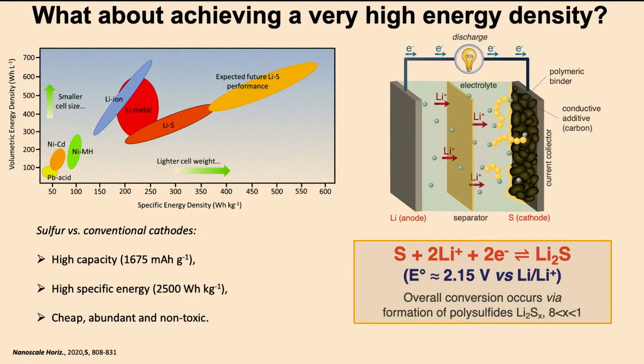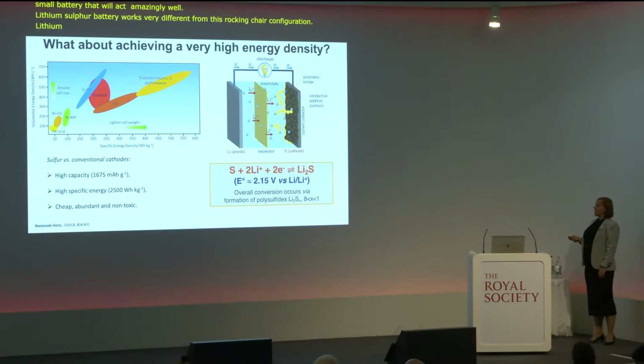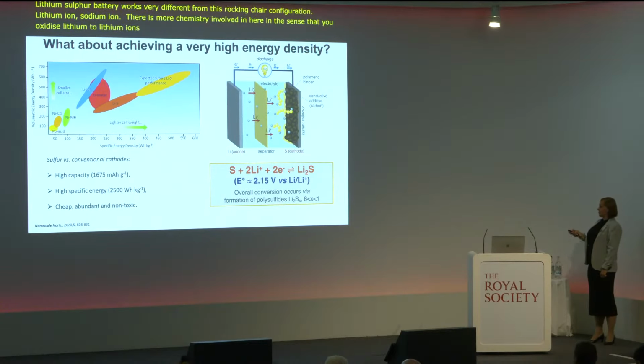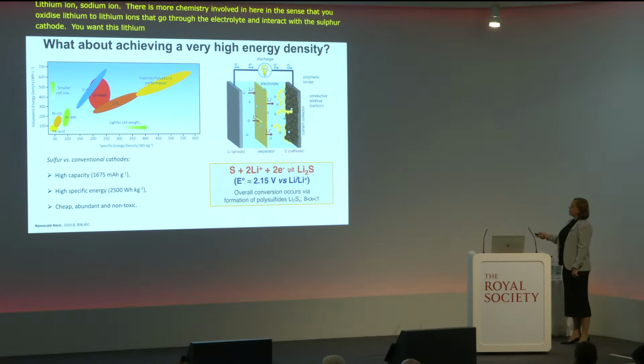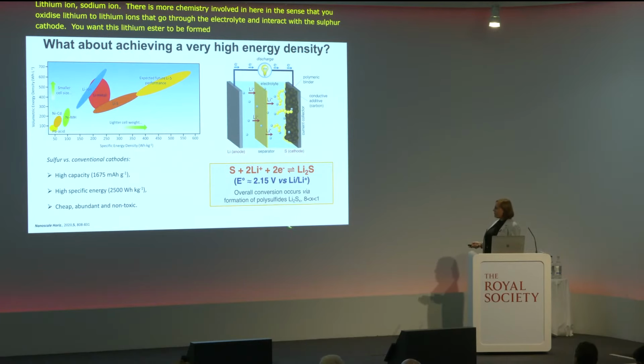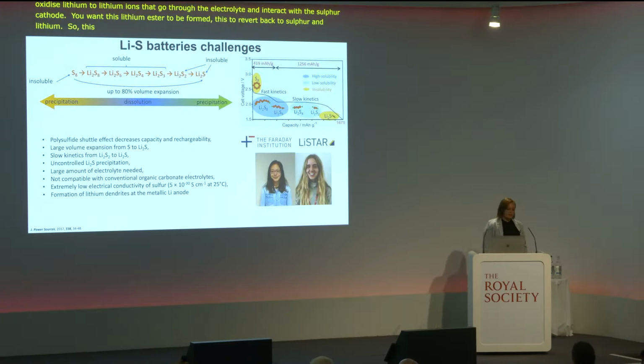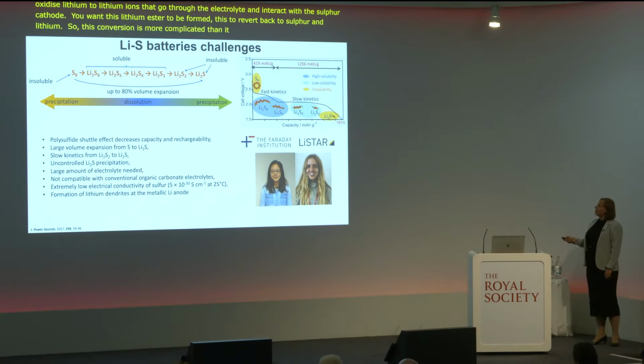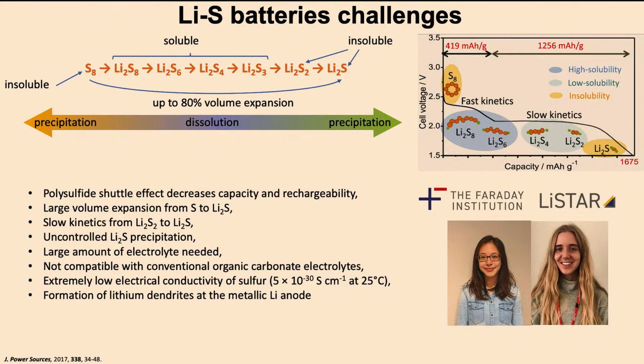Now, lithium-sulfur batteries work very differently from the rocking-chair configuration of lithium-ion and sodium-ion. There is more chemistry involved, in the sense that you oxidize lithium to lithium ions that go through the electrolyte and interact with the sulfur cathode, and what you want is Li2S to be formed. And then you want this to revert back to sulfur and lithium. This conversion is more complicated than it should be, so unfortunately you don't go directly to Li2S, but through a lot of polysulfide intermediates. Some of these polysulfides are soluble in your electrolyte, so they plate back onto your lithium anode. You're going to lose your cathode. It's called polysulfide shuttling.